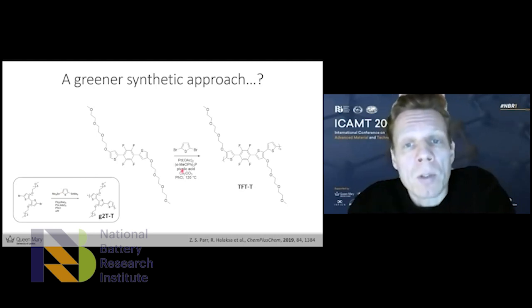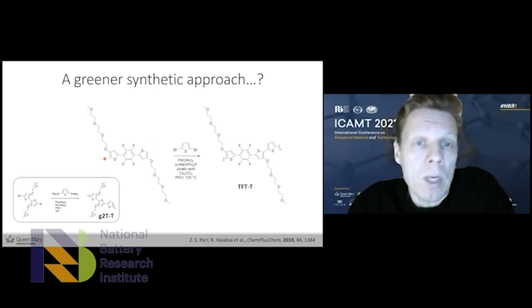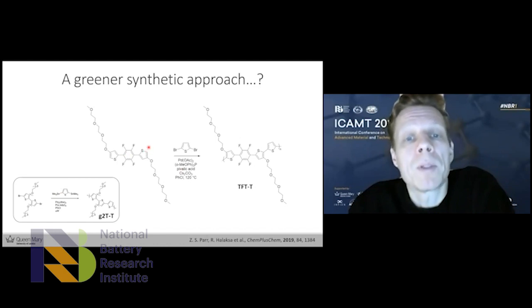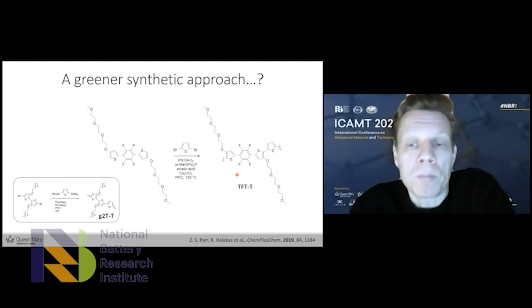And this process here is called the direct arylation polymerization, where we avoid these organotin reagents and we get a direct coupling between the aromatic system here, just with hydrogens in the active positions, and a dibromide, a thiophene dibromide as the coupling partner. And we showed that works quite nicely, so we can surpass the use of organotin reagents. And we made this new, again, glycolated polymer here to investigate for mixed conduction properties and eventually bioelectronic applications.